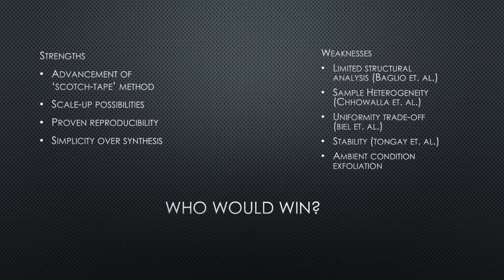While the high throughput exfoliation method was the main strength of this paper, it could have benefited from a deeper discussion on the actual trade offs of this method, rather than just discussing its throughput and uniformity. The study also primarily focuses on fresh mechanically exfoliated samples under controlled conditions. However, it does not mention how these materials might hold up over time at ambient conditions, whether degradation is a factor, how quickly these would degrade, and any potential damage induced during the manufacturing process of these materials.